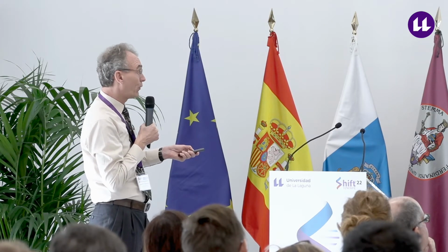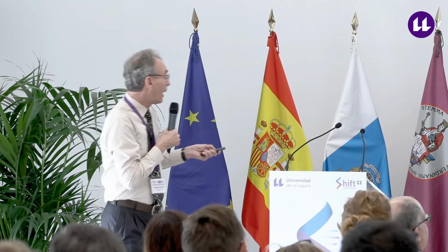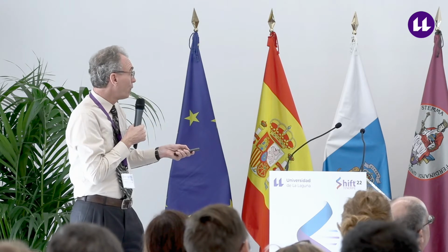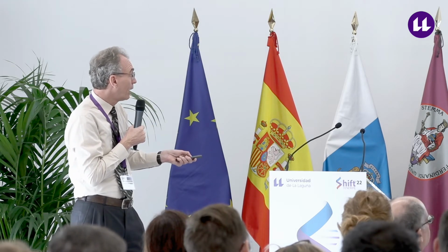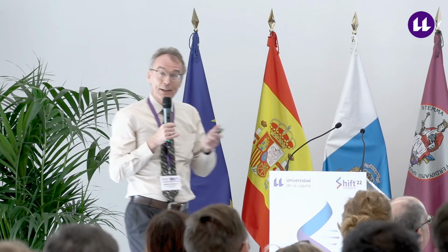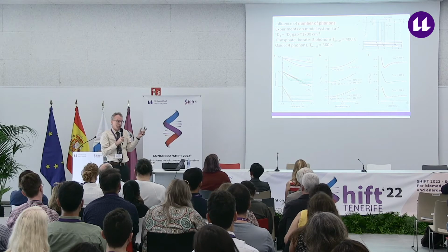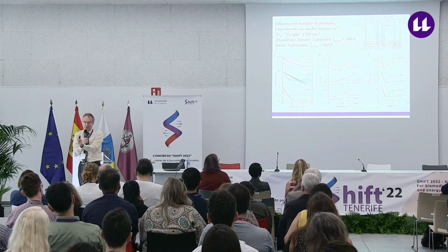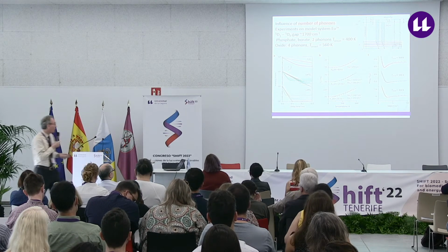But the temperature is 560 Kelvin, very high temperature. When you go to the higher phonon lattices, the phosphate or the borate, then you see it's already around 400 Kelvin. And that's important, and people often ignore that. They assume that they have Boltzmann equilibrium, but in some of the thermometers that are reported in literature, at the lower temperature end, they are not in Boltzmann equilibrium. You see deviations, and then you get the wrong temperature when you use the Boltzmann equation.